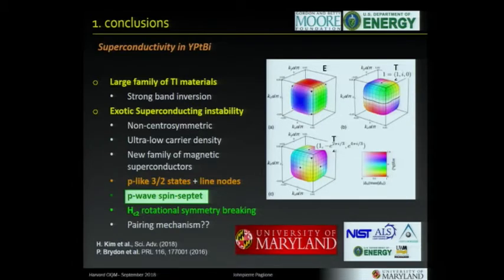So I'll just summarize now. The Heusler family is quite rich. It's a large family. Even just the predicted topological materials are quite large in quantity. So we're exploring different types of those, and even looking at how you can substitute this continuously and try to change the spin orbit strength, for instance. The superconducting state, as I've shown you, is quite exotic. First of all, because there's no inversion symmetry, so you have these Rashba split states. You have a mixed parity. The carrier density presents a challenge in understanding what's actually pairing it. You can mix in magnetism.